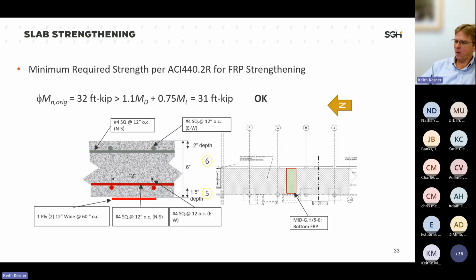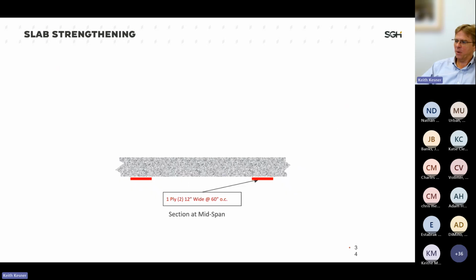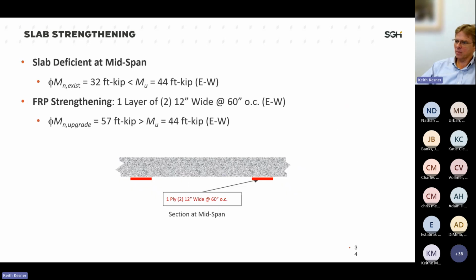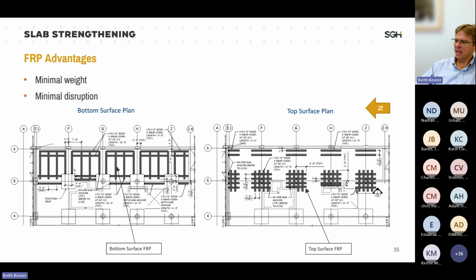Again, looking to confirm that the minimum strength was satisfied. Again, it's one strip of FRP on the bottom side, now 60 inches on center. So some simple calculations at the midspan. And then, what does it end up looking like? Depending upon where you are, bottom surface, top surface, different amounts of FRP are bonded in to allow for strengthening of the one-way plate, where most of our strengthening is actually added in our negative moment regions near the columns.